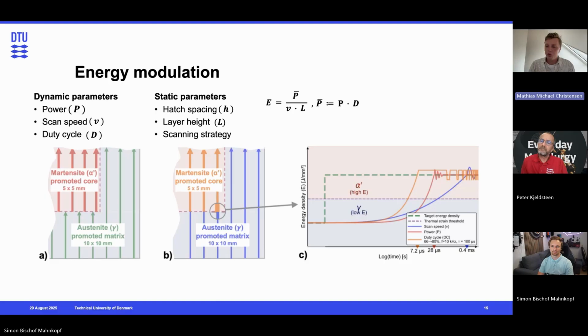Yeah, but maybe we should also explain how we devised the volumetric slicer. Yeah, just quickly, I want to add that these response times might seem very low when we're talking not just milliseconds, but sub-milliseconds and microseconds. It might not seem significant, but when you're looking at a very fast scan speed, so we only printed at 400 and 600 millimeters per second, but in the industry, they go up to several thousand millimeters per second. You actually see that these times can be a significant distance when you move at that fast speed.